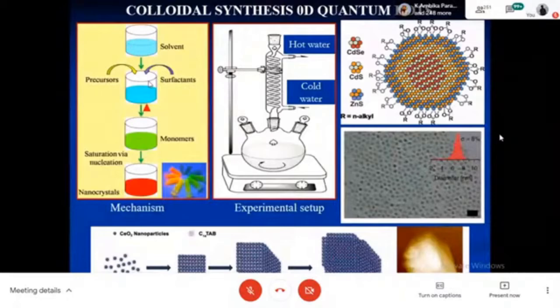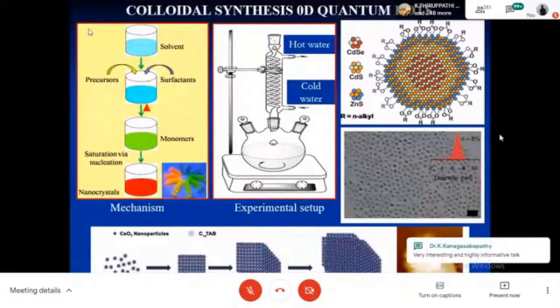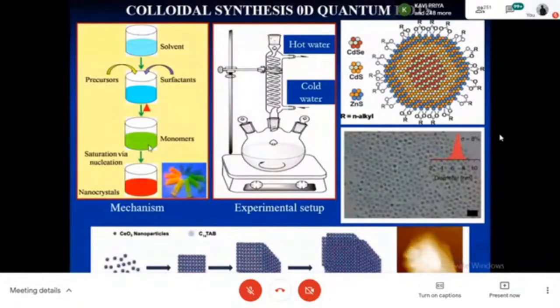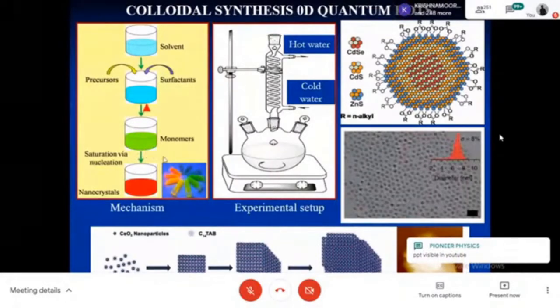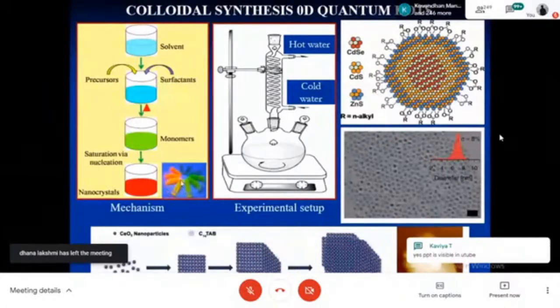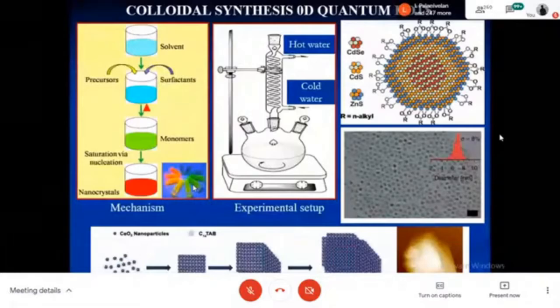So if it grows further, then it becomes what is called bulk material. It is no longer a zero-dimensional structure. So we take the precursor with the surfactants, and then we optimize the conditions where the monomers are formed. And then these monomers can be converted into clusters through the nucleation concept. And once the nucleation is induced and it grows to a critical size, it forms a nanocrystal. And these nanocrystals, depending upon the size, as I said in an earlier slide, can absorb different wavelengths. And because of the variation in the absorption of different wavelengths, we have different colors of these nanoparticles. And this is by simply varying the size of the particle.